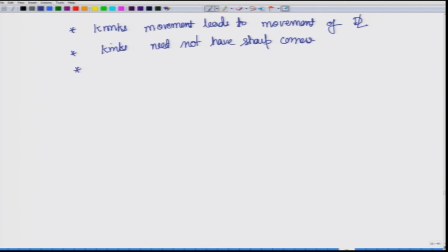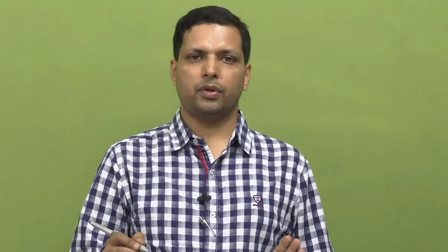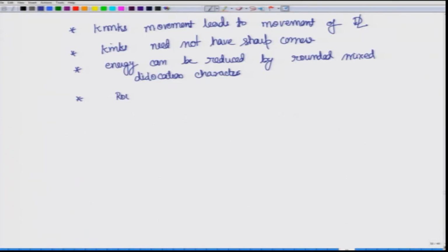And what has also been analyzed is that the energy of the system can be reduced by rounded, mixed dislocation characters. Another thing that people who have studied dislocations in greater detail have found is that this roundedness, how sharp or how rounded these dislocations are, depends on the Peierls-Nabarro valley. So roundedness also depends on the PN valley. And this will become clear when we look at